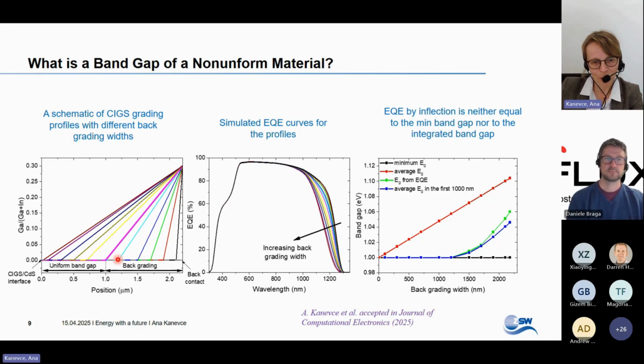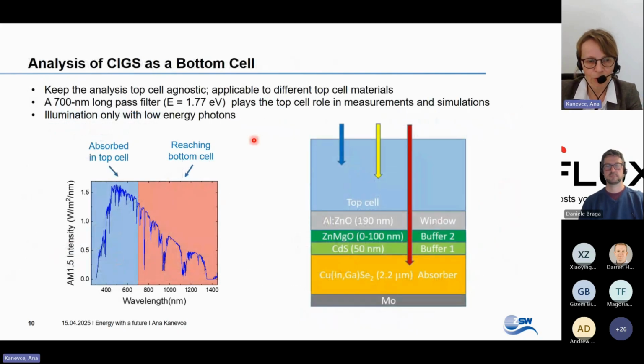Now I will switch to the bottom cell. I will show you some experiments and some simulations. I will keep the whole discussion top cell agnostic, so the top cell is just presented with this blue box. It is simulated and measured with a 700 nanometer long pass filter. 700 nanometer corresponds to a bandgap of 1.77 eV, which is the bandgap of some wide bandgap perovskites.